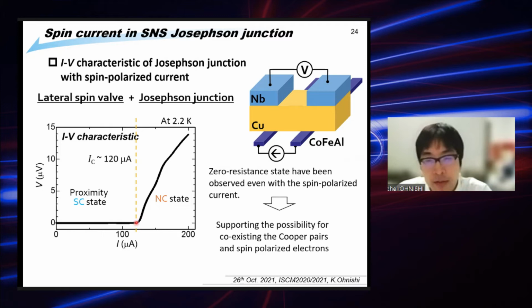This is a very typical, common IV characteristic of the Josephson junction. Below the critical current, there's zero resistance, which indicates the superconducting state, and over the critical current, there's a resistive state. But here, this is very special because we measured this IV characteristic with a spin polarized current by using these cobalt iron aluminum probe electrodes.